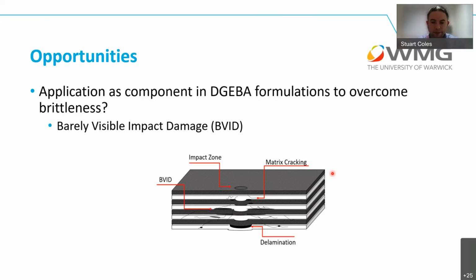epoxy resin formulations? And one of the things that we started to look at was this phenomenon known as barely visible impact damage, this BVID. What you have here is effectively an impact zone where maybe in composites, maybe a tool in a workshop, a hammer or something is dropped onto the composite structure, and you see very little damage on this top surface, but actually you've got cracks and fractures propagating all the way down through the system, and maybe some layers down you've actually got complete delamination of the material. And this kind of barely visible impact damage is a real problem in a lot of different composite structures. So if we have a way of mitigating this in some way, this might help us.